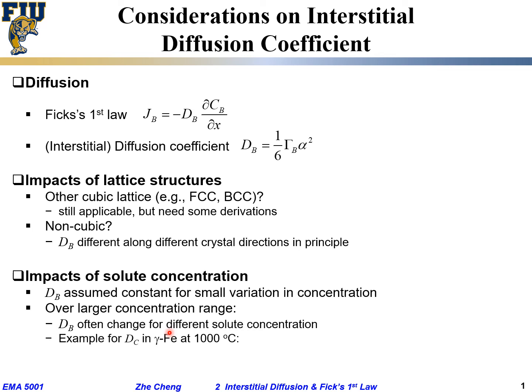How much change? We give one example: DC for diffusion of carbon in gamma iron, which is the FCC structured iron austenite structure, at 1000°C. What people measured in reality is 2.5×10⁻¹¹ meter squared per second for 0.15 weight percent of carbon.